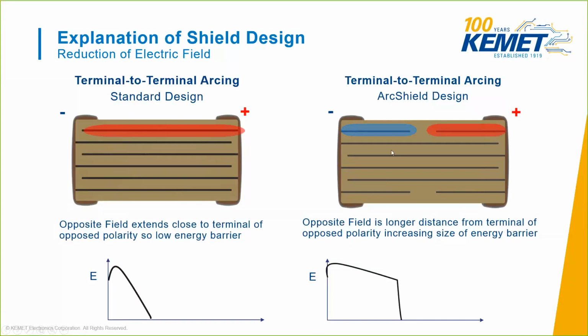But in the terminal-to-terminal arcing situation in an ArcShield design, you have this same polarity as the termination electrode extending out towards the center of the chip, and this increases the energy barrier as a function of distance across the chip. So now you don't have this opposing electrode with the termination providing this shield, which is why we call it the ArcShield technology for this MLCC structure. So now we can create a much stronger dielectric in the center of the chip, allowing us to create more and more active layers and increase the capacitance without the risk of arcing along the surface.